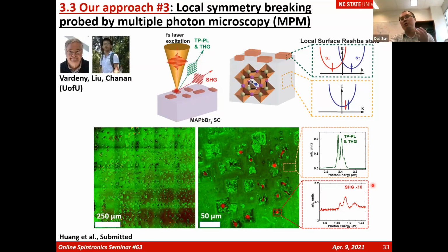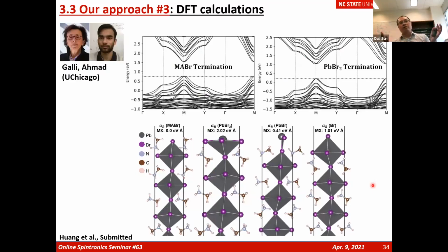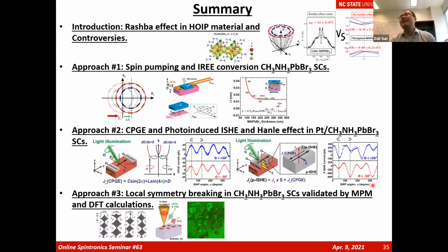In order to further prove our local Rashba state formation, we asked the University of Chicago, Professor Giulia Galli's group, to do the DFT calculations. We found that even though the bulk material is the same, still the MAPbBr3 bulk might contain the same lead and same organic cations, depending on the surface terminations, the Rashba state can be changed significantly. By exposing more bromine or more lead on the surface, the local terminations determine the strength of the Rashba effect. So that answers the question: does the Rashba state exist in the MAPbBr3 single crystal? Yes, but locally.